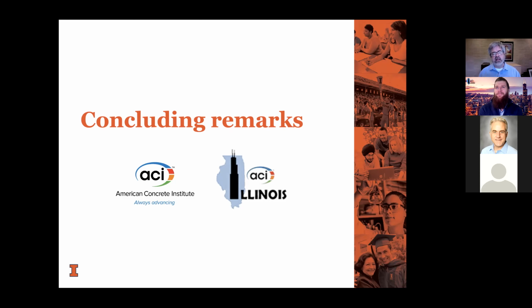As a general rule, the basic behavior of concrete is not going to change very much by the presence of SAP. The water cement ratio, everyone knows, is the big daddy. That's the one that changes the slump, changes segregation properties, changes set time even, and so forth. So as a rule, we did not see changes to set time. Even having this SAP in the microstructure didn't affect that too much. And I mentioned strength, it didn't change that, and all the different strengths.